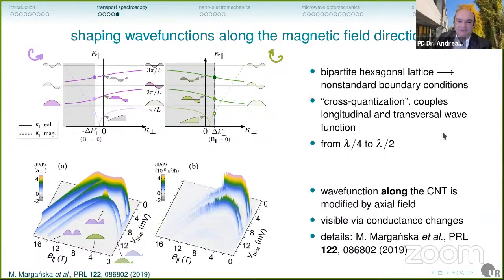You end up with a term that makes a cross-quantization, meaning it couples the longitudinal and the transversal wave function in your trapped system. And you can tune the trapped electron from a lambda quarter shape, like this here, to something like lambda half shapes. And now, of course, the strength of the wave function near the contacts dominates how strong your tunneling goes. So these effects become visible in the overall conductance. If you plug this model into a tunneling calculation, then you see that we can reproduce, for example, that these lines here disappear rather nicely. So this just as an example of what you can do in terms of transport spectroscopy on such a system.